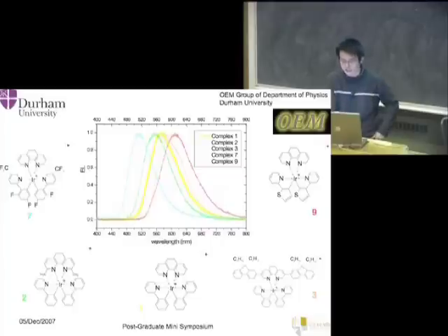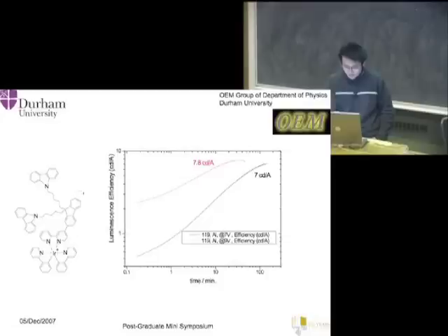And I was just talking about the low efficiency comes from the strangely high current. And this one was what we got at the beginning of this year. And this is the molecule we tried. With this one, because we made the film thick enough, maybe this will reduce the effect of the short circuit. So this one we get a pretty good brightness and efficiency as high as 7.8 candela per amp. But because the film is thicker, it requires longer time of charging. You see, we're talking about something like 30 minutes. But for my previous device here, it only requires like 3 minutes or so.